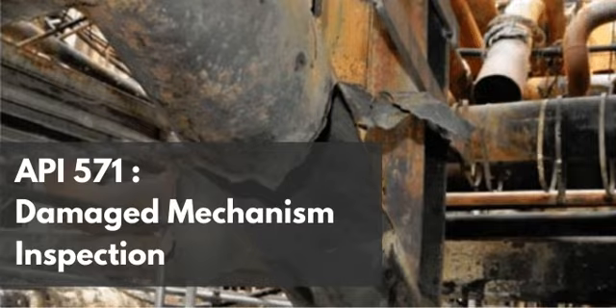Exactly. When a solid lump of coke deposits and latches onto the inner wall of that roaring heater tube, it is essentially pure, concentrated carbon in direct, intimate physical contact with the hot steel matrix. Just pressed right up against it. Yeah. You do not even need the gas phase carbon floating by at that point. The solid coke is acting like a high-pressure carbon injection system right at the surface of the metal, driven deep into the lattice by the intense radiant heat coming from the firebox on the outside of the tube.